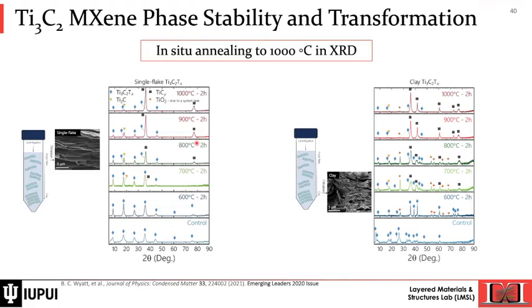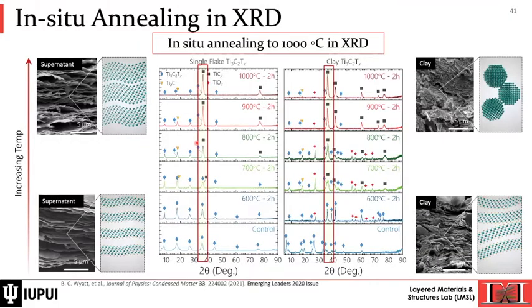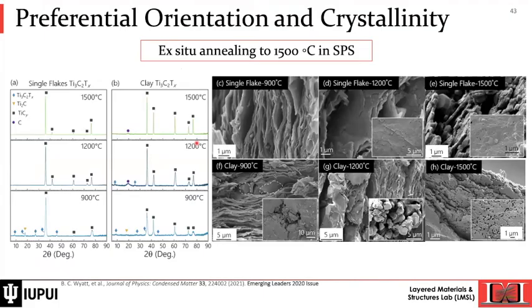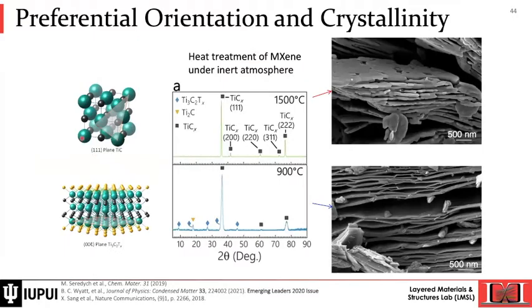So I'm going to skip through all this and just bring it to here. You see that if we take it to higher temperatures, even 1500 C, the titanium carbide that we form is highly textured, meaning that we have only the 1-1-1 plane of TiC shown in the XRD, because they're growing off of the basal plane of a hexagonal structure, which is identical to the 1-1-1 plane of TiC.